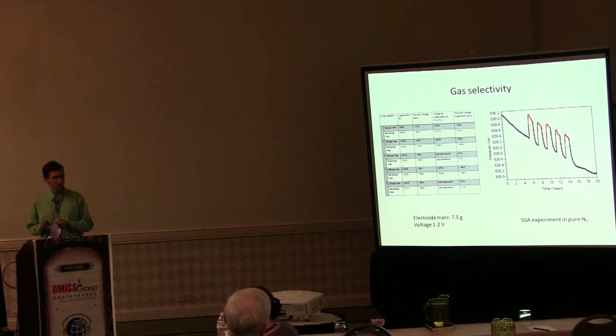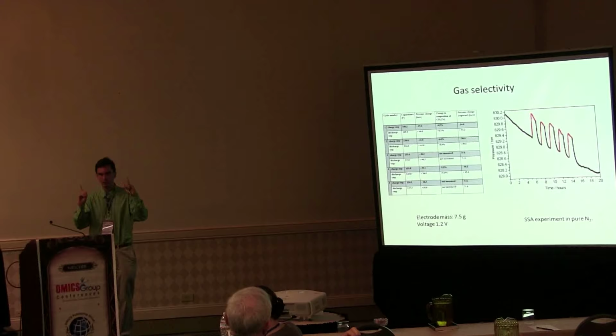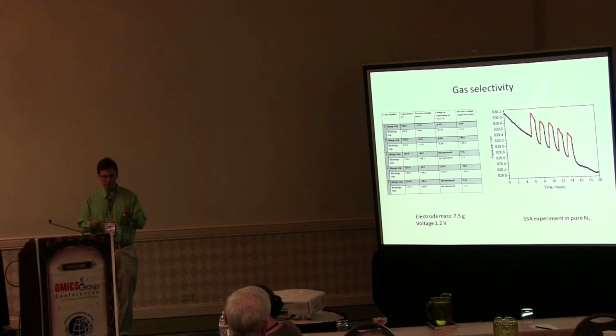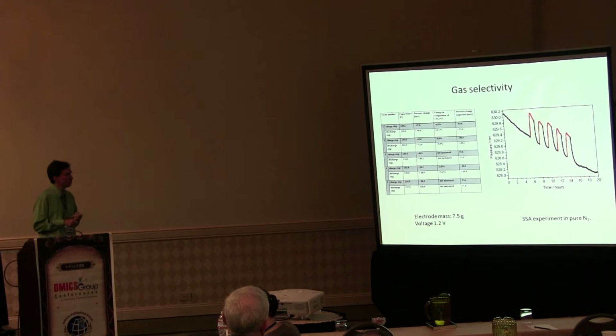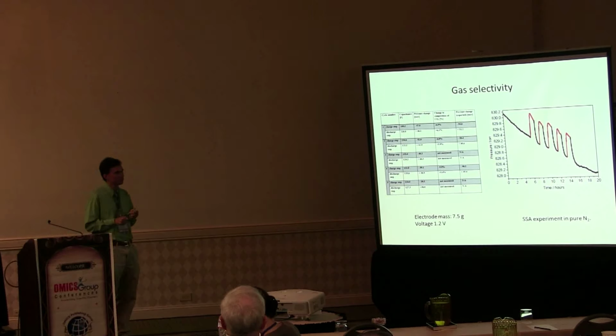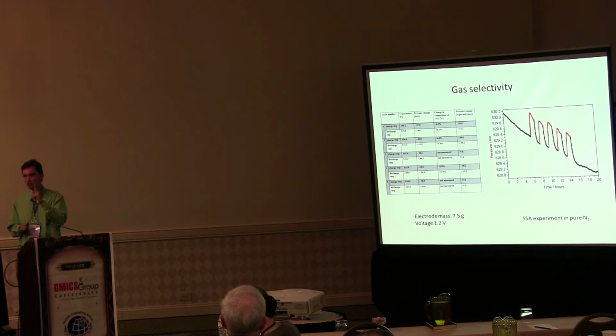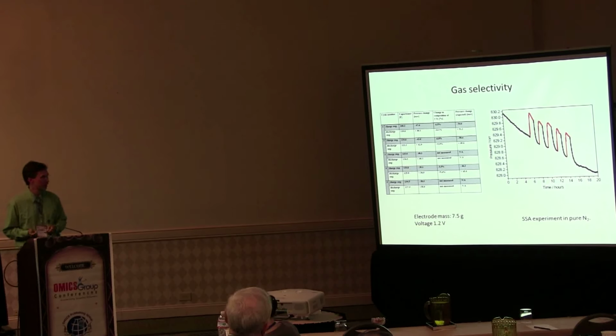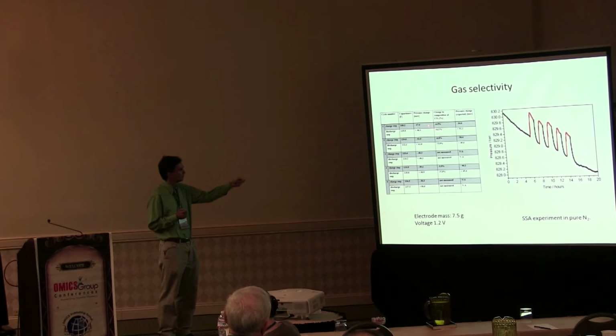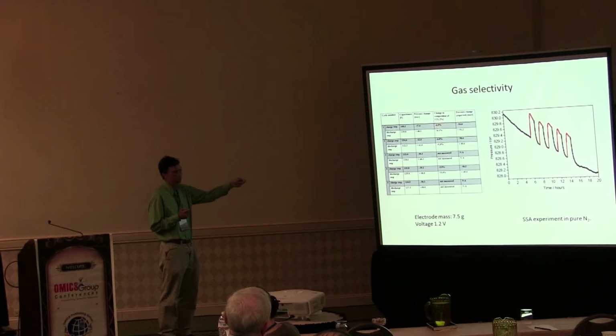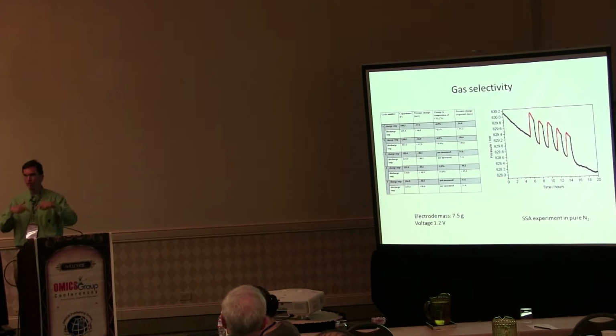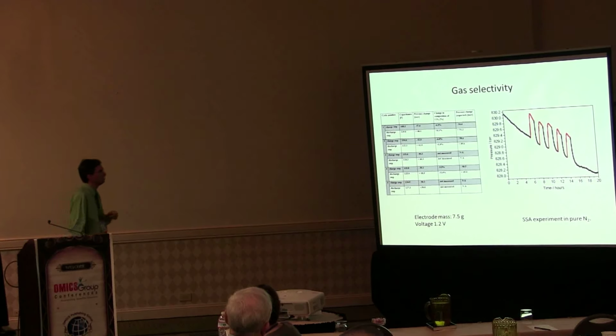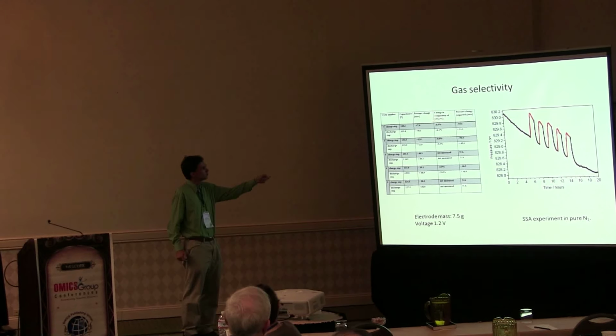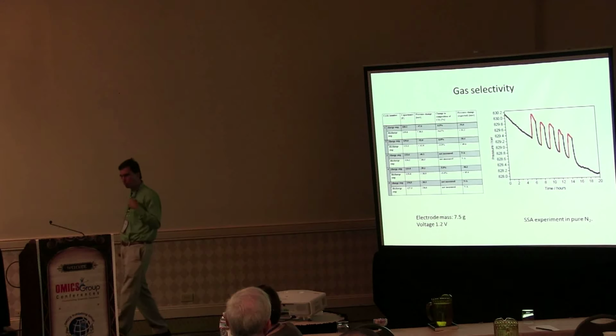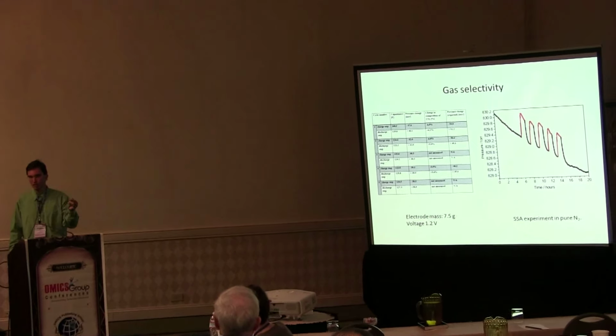In addition, we were interested in the question: what is our gas selectivity? Are both gases in our gas mixture equally adsorbed, or is there a gas selectivity? To find this out, we did gas chromatography at the beginning and at the end of each half cycle and measured the gas composition. You see that at the end of one half cycle, the gas composition has changed by about 6%. This means the composition changed from a 15% CO2 content down to approximately 9% CO2 content. In a discharge step, we see that the CO2 content increases by approximately 6.1%. That shows that the adsorption is reversible.